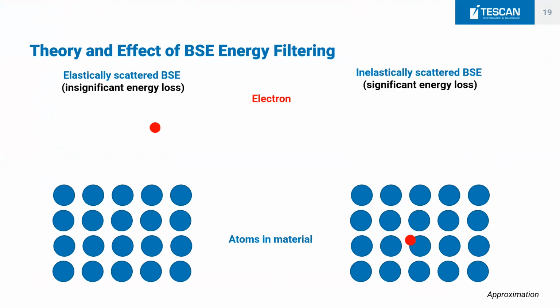Or we have inelastically scattered backscattered electrons. They travel deeper in the material, and by the fact that they travel deeper in the material, they lose a lot of energy. So imagine that you have a primary electron energy of 1 kilovolt, and it wouldn't lose energy. The escaping energy would still be 1 kilovolt. If you have inelastic scattering, it would lose 500 volts, and it would have 0.5 kilovolts.